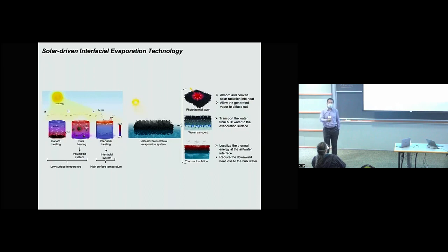If you carbonize the material, you can improve its solar absorptivity. Also this material must normally be porous. Porous material can absorb water easily due to the capillary force, and hydrogels also can absorb water easily, from the bottom to reach the light absorbing layer at the top.